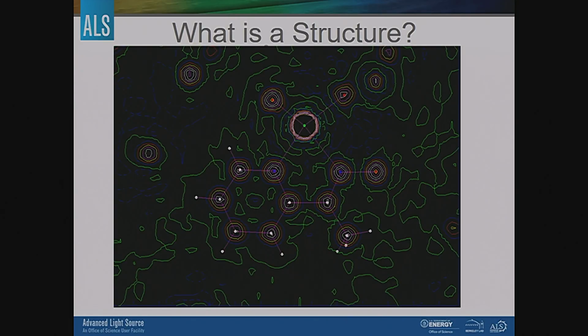All right, so this is the idea of what we get initially: we get a solution. So we get some electron density. And so you can see this is a map, and we have something very heavy here. So we have lots of our little gradient lines because there's something very large. And then we have 6, 7 rings. I believe I rendered these all at about 1 electron per cubic angstrom. So you can see, okay, we've got light atoms, something heavy, something possibly heavy but not quite in the plane, something weird over here. So we get a 3-dimensional map of where atoms could be.